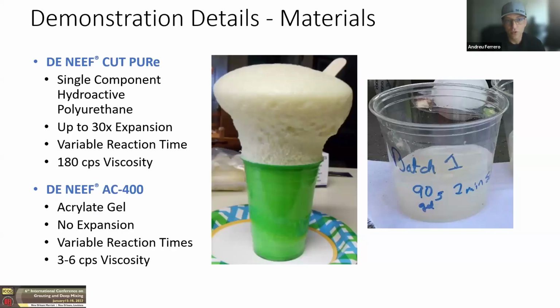That material reacts when it comes into contact with water, and then it expands. As you can see in the photo, it expands upward in a rigid body. And then once it's done expanding, it becomes hard and is not flexible. It provides a barrier to water ingress, and it also stabilizes soil.